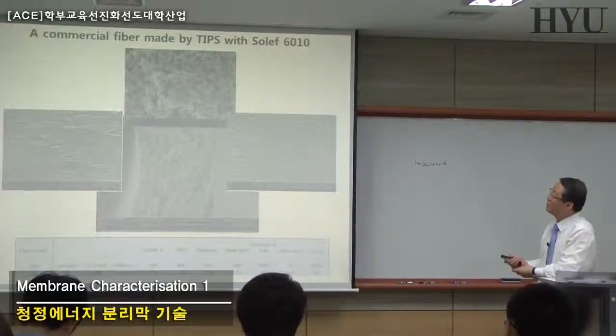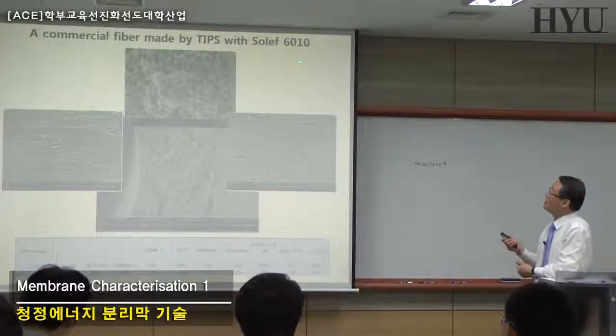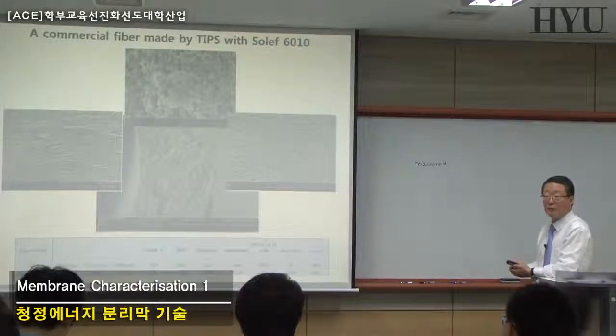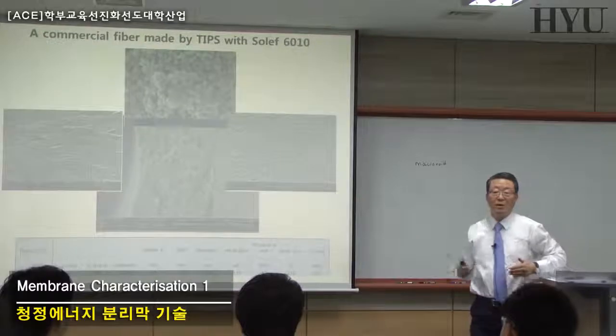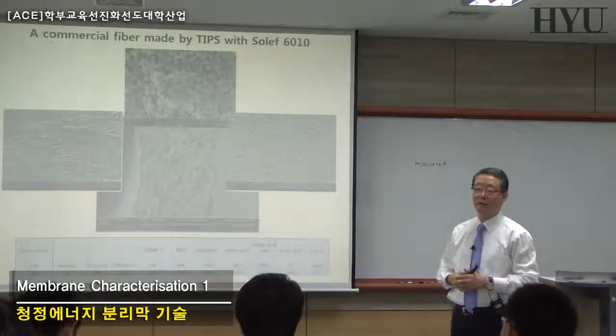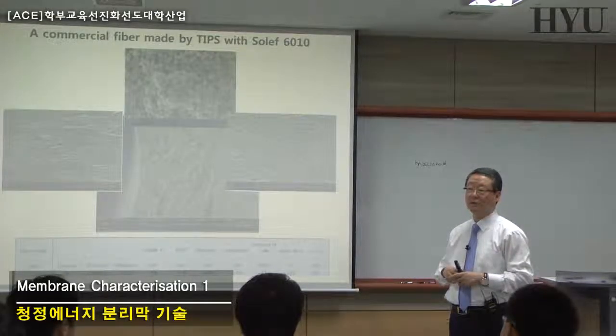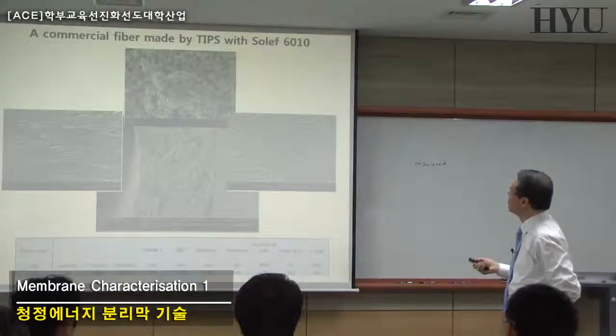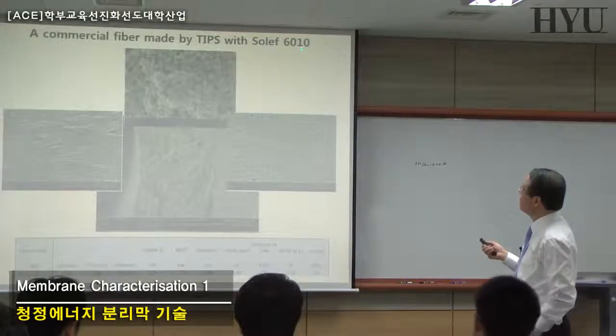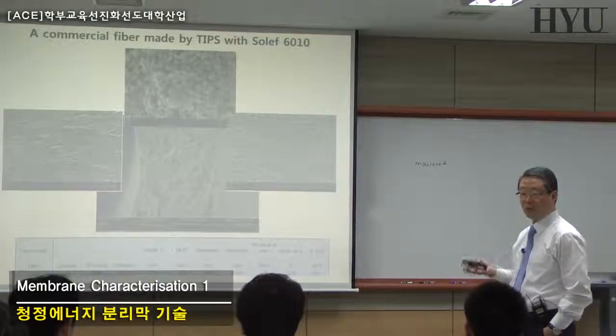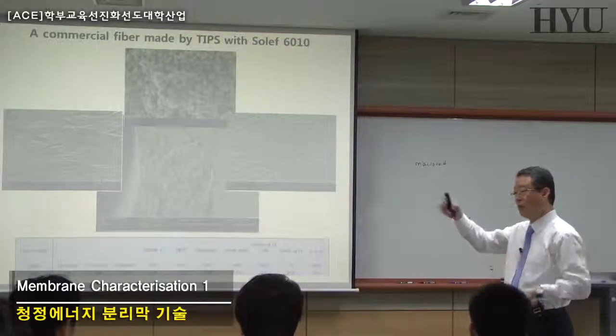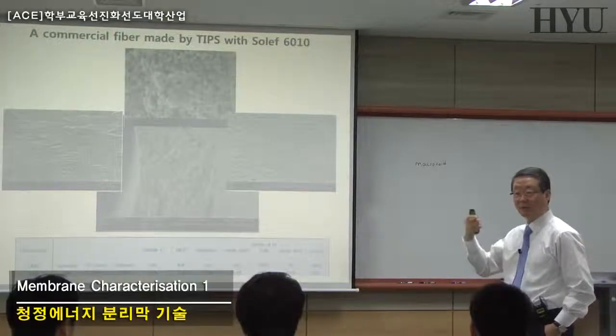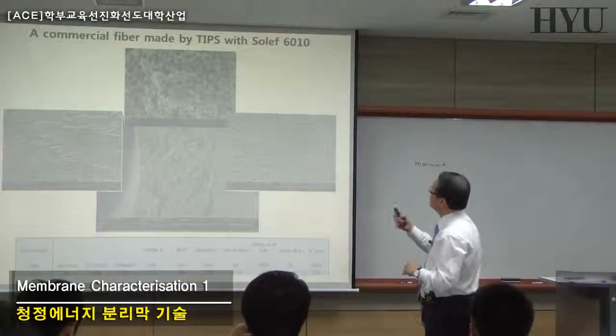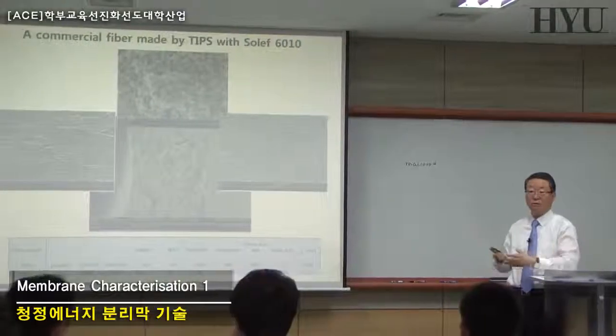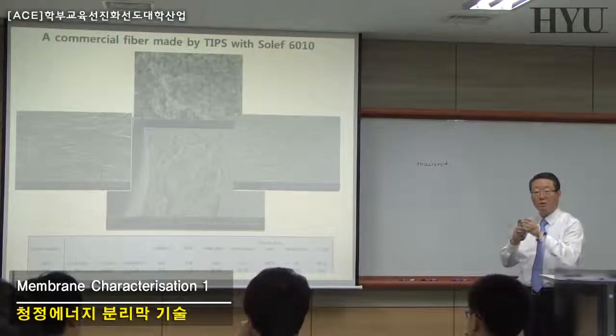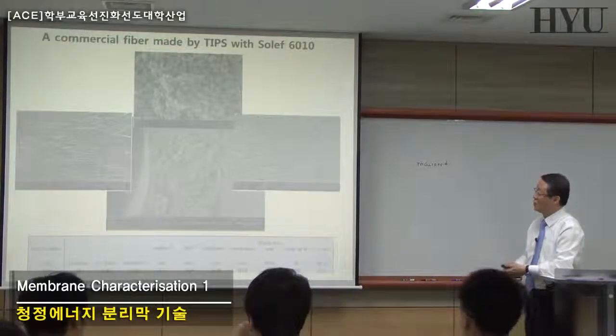And this is the typical example of the TIPS process using the Solef 6010. 6010 is a typical grade of Solvay PVDF polymer, and they have various types of PVDF ranging from 300,000 molecular weight up to about 700,000 molecular weight, and they have different names. 6010 means that this is the first product. They may have a 6015, 6020, 6030, 6040, stuff like that. And the higher number means that you have increased molecular weight. Using these several grades of PVDF, you can make a typical PVDF hollow fiber membrane with porosities.